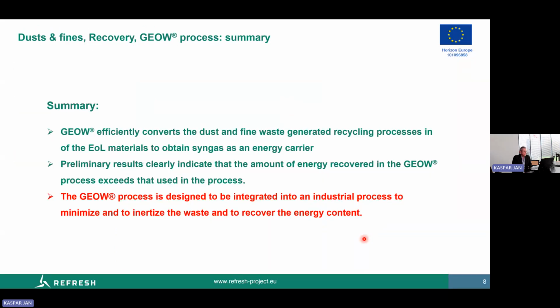So coming to the summary, I think that we have shown that this pyrolysis reaction is able to convert these materials and obtain syngas, which is a useful energy carrier. Preliminary results, as I said, not optimized, show clearly that the amount of energy recovered exceeds that used in the high temperature treatment. And essentially, what is the idea of the GEOW project? It is designed to be integrated within an industrial process. This is an important aspect because as long as you move the waste within the project, it's not classified as waste. The waste will be the final product of our process, which, however, we can inertize even if toxic. And most importantly, we recover an exceeding value of the energy content.